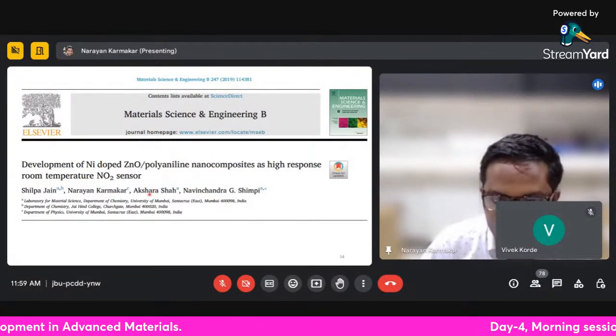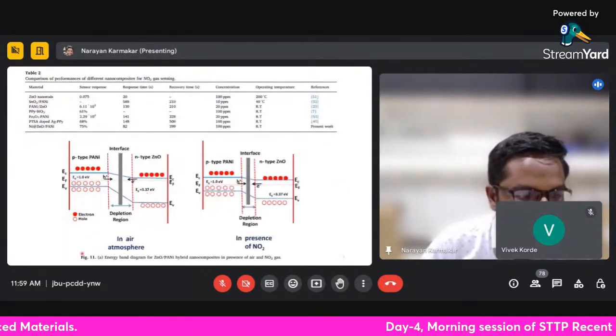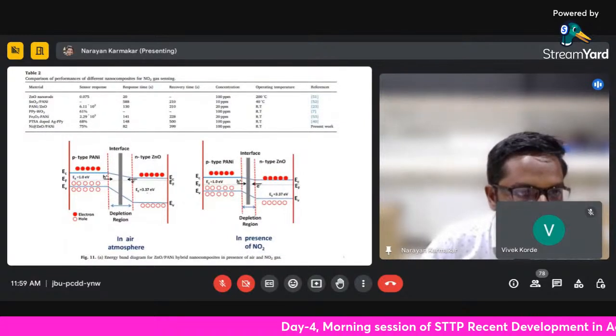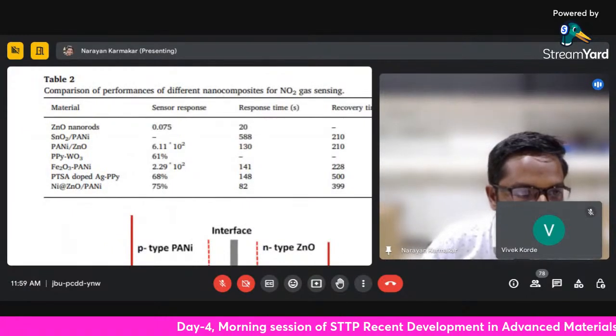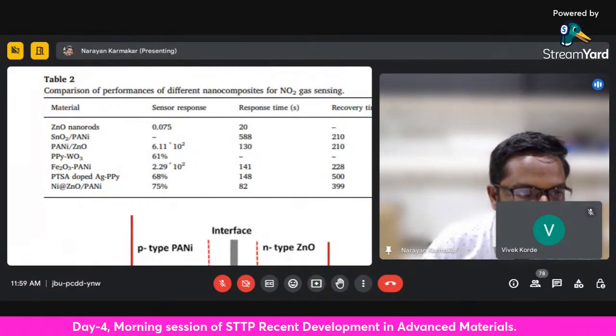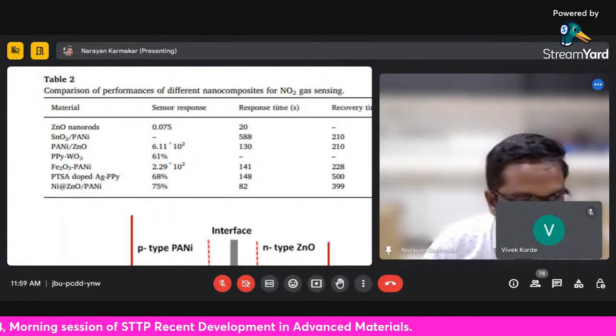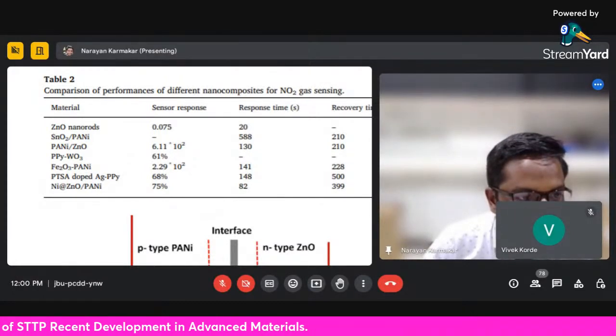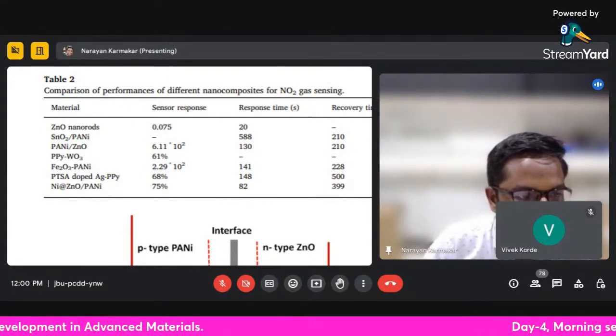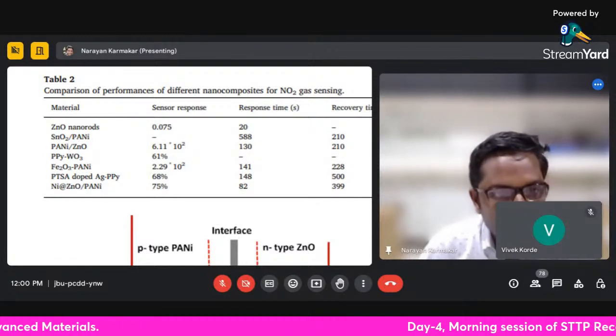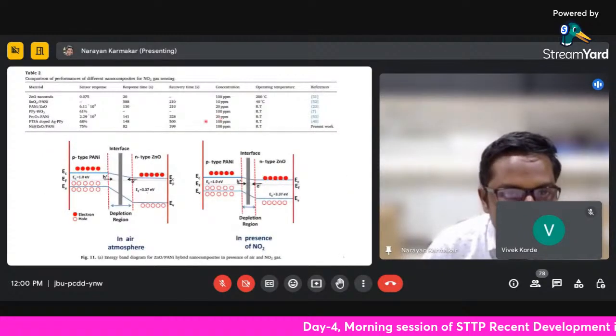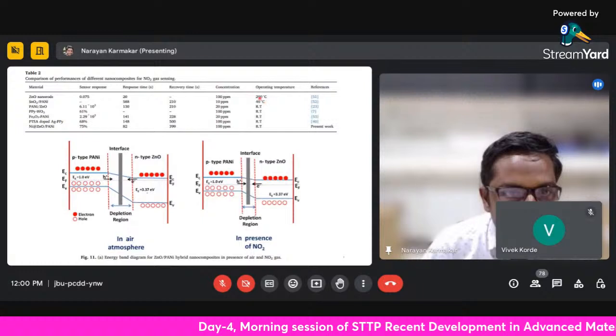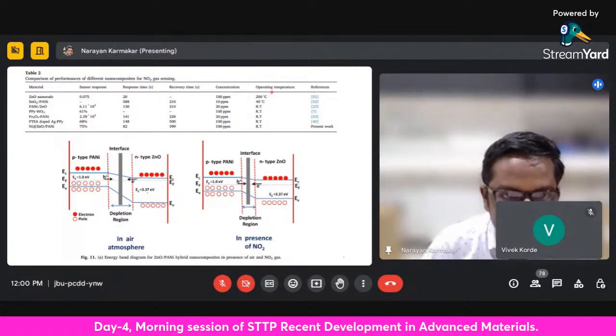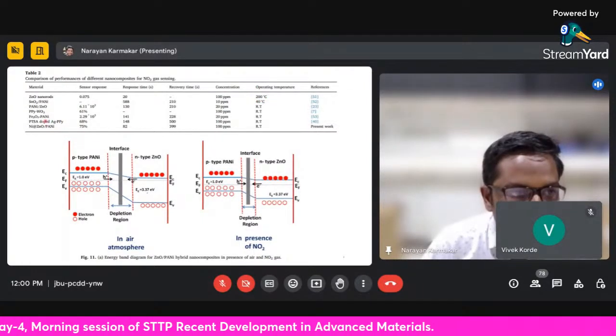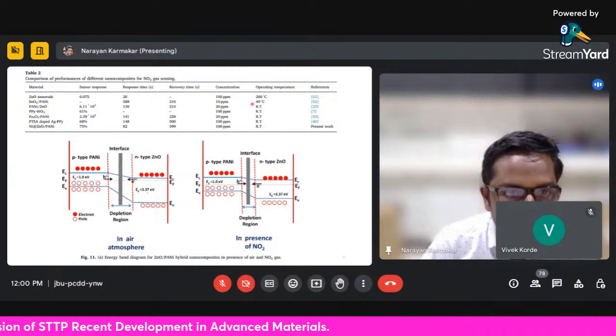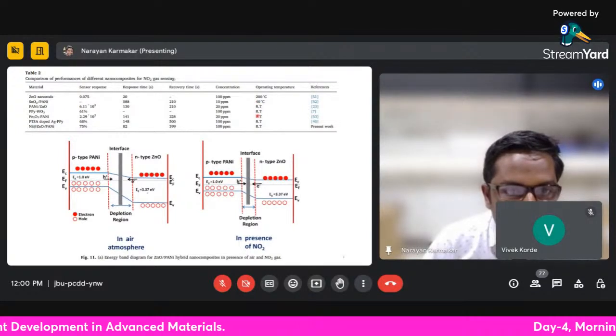So what exactly is happening here: look at this graph. These are the readings of zinc oxide nanorods, tin oxide, PANI nano, PPY, tungsten oxide, and all these materials. We can see the sensor response here. But look at this: the zinc oxide nanorods operate at a temperature of over 200 degrees Celsius, but when doped with the conducting polymer, it works at room temperature.